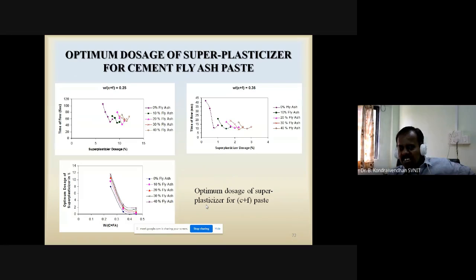Okay, so as I mentioned earlier, first we determined the optimum dosage, because our intention is to determine the pore size distribution. So we have to ensure complete dispersion of the cement particles. Otherwise, we cannot get complete hydration, because hydration needs some space between the particles. Whenever you use superplasticizer, it gives a negative zeta potential. That's how the cement particles get dispersed properly, and there is space available for the inner product and also the outer product, that we can achieve by using the superplasticizer.